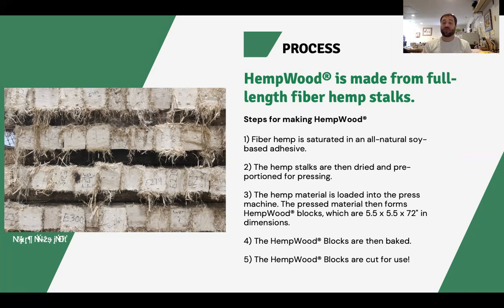Just like having a 200-year-old tropical hardwood, we're making a four-month-old hemp stalk perform with similar attributes — so you don't have to cut down beautiful Brazilian cherries in the rainforest, only to have them take 10 generations to come back to their mature status. You can do it every spring to fall. The hempwood blocks, after they're pressed, are baked at slightly above boiling temperature, which causes all of those proteins and the cross-linking agent to link together. Then the blocks stabilize for two weeks and are cut into their intended use, with flooring as our primary product.